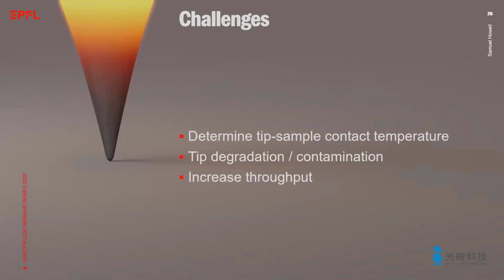So this leads me to the challenges of t-SPL. One of the challenges is to determine the tip sample contact temperature, which is difficult to compute. In particular, for understanding the thermal processes at the nanoscale, knowledge of the temperature is very valuable. However, for patterning, for example, knowledge of the temperature is not necessary, because the feedback from the topography changes is often enough to determine if a reaction took place. That is why it's nice that with t-SPL, one can use the cold tip to scan the substrate and directly detect whether a modification took place.